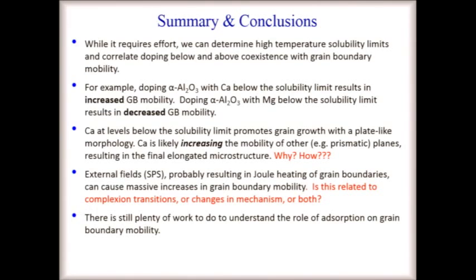And there's enough other evidence in the literature to show that disconnections are the culprit. And what changes with disconnections being emitted from triple junctions, I think, is what's really exciting here in these mechanisms. Of course, complexions go with this, or adsorption, or BOP, whatever we want to call it. But that phenomenon is going hand in hand. We're changing the chemistry and structure. It's going to affect the way the boundary moves. And that's pretty much trivial.